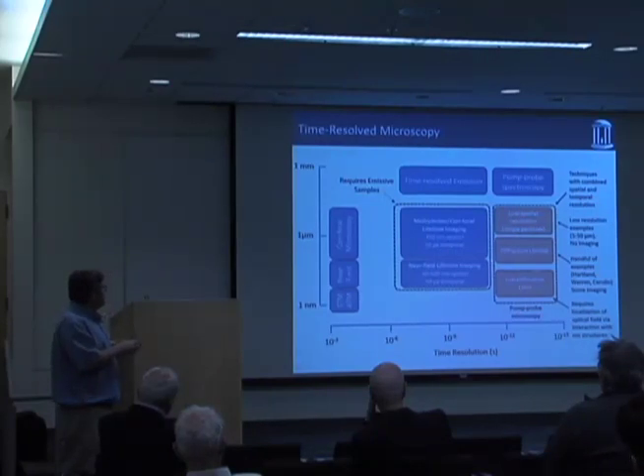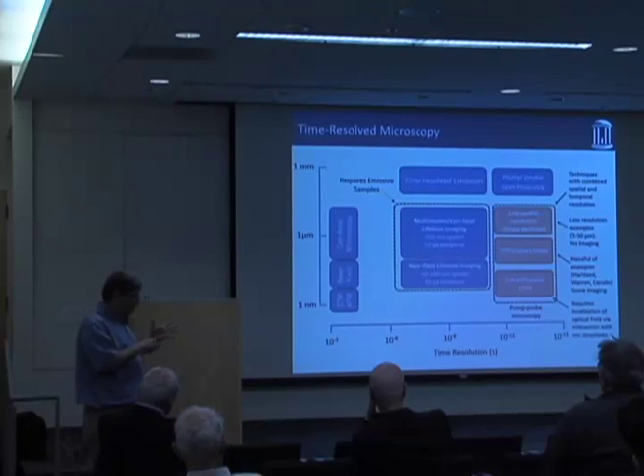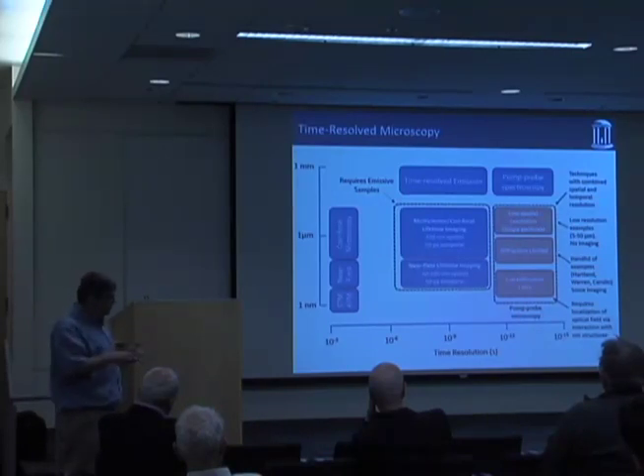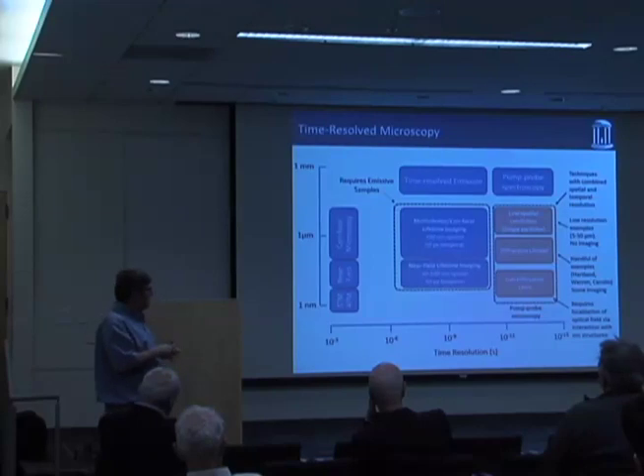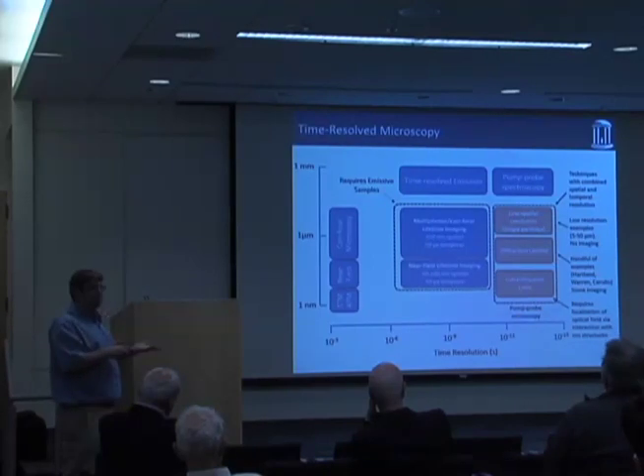And so we backed up and said, okay, let's try and do conventional microscopy, but do pump probe spectroscopy in the microscope. And so we've been working in this range. Our spatial resolution is a few hundred nanometers. Time resolution is a few hundred femtoseconds. And so we've tried to pick problems that match those limitations.